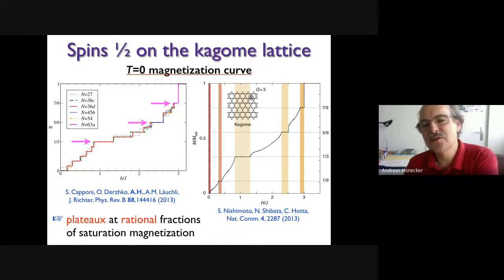The right panel shows you a similar computation by a different group that used a different method, but the conclusions are the same. They see the same 3 plateaus. And they might have seen another plateau at 1/9 of the saturation magnetization that we were unable to resolve. Okay, so the upshot is there are exciting phenomena like magnetization plateaus at rational fractions of the saturation magnetization in such highly frustrated magnets. And although I picked here 10-year-old work, there has been recent progress, so these problems have been investigated further. There's more recent work, and there are other things that you can discuss about that.